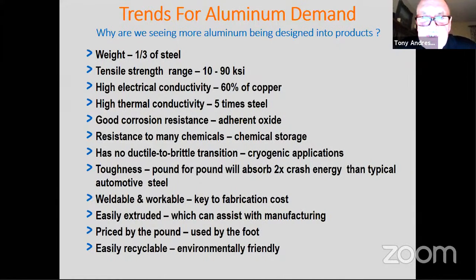Okay, good corrosion resistance, absolutely. But why does it have good corrosion resistance? It's because it has an adherent oxide. And aluminum oxide is a strange animal. It has some weird characteristics, one of which is that it melts at 3 times the temperature of aluminum. So aluminum melts around 1200 degrees, aluminum oxide 3600 degrees. So is that an issue? Well, yes, certainly can be, because it can act as an insulator when we try to weld. So we need to address that when we pre-clean and prepare for welding, most certainly.